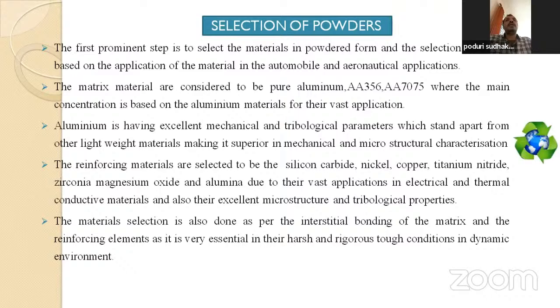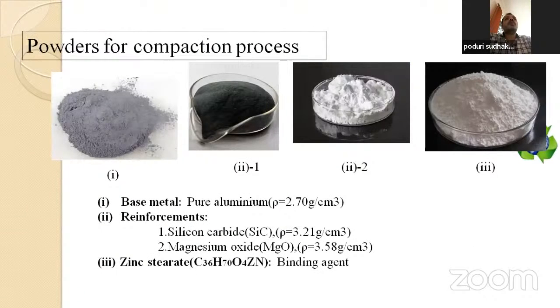I already discussed that I have taken not only pure aluminum but also 356, 7075, 2024, and all kinds of alloys. The reinforcements are silicon carbide, nickel, copper, titanium nitride, zirconia, magnesium oxide, and alumina. I have considered them due to their electrical and thermal conductivities, and also to have high surface finish, microstructure, and tribological properties. We know that pure aluminum has a density of 2.7 grams per cubic centimeter, and silicon carbide has more than aluminum, 3.21. Magnesium oxide is much more, but it is of a brittle nature. That's why the bonding is low. Even though the density is high, nickel has a higher density when compared to all of these.